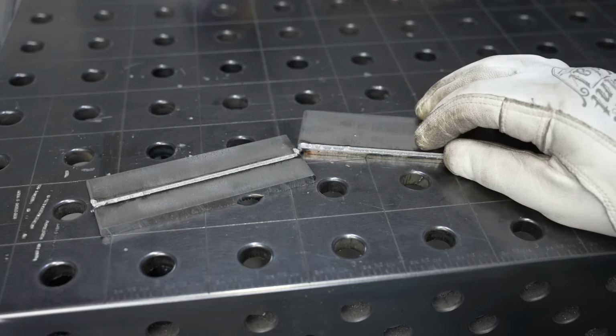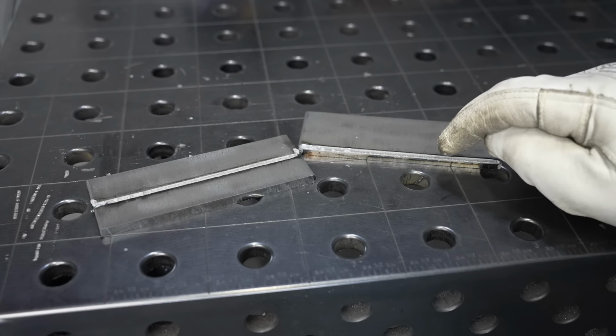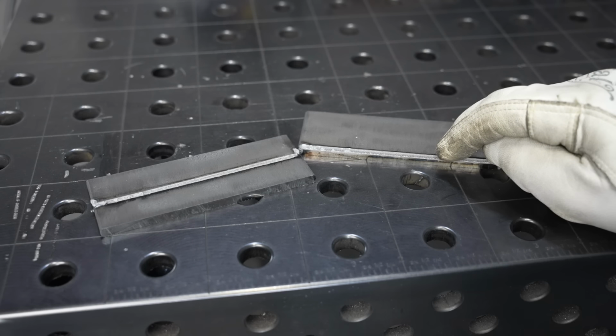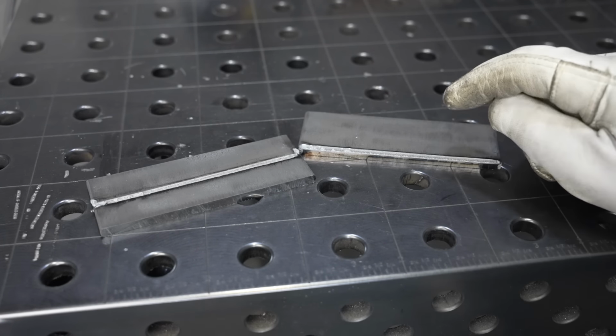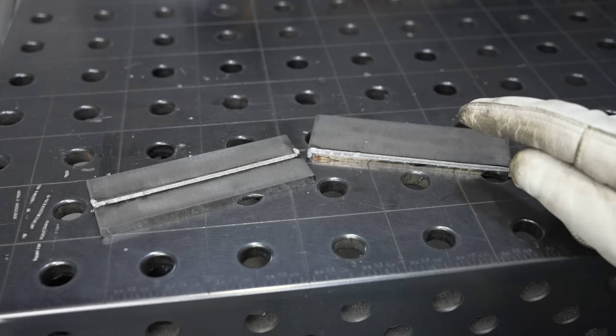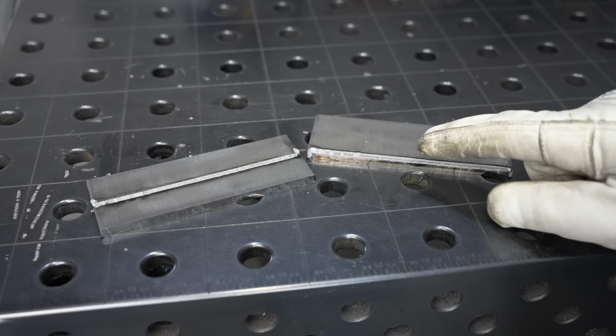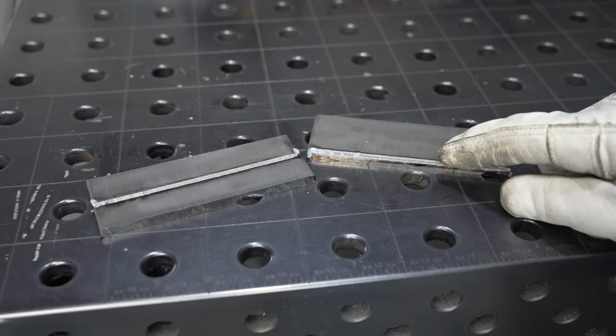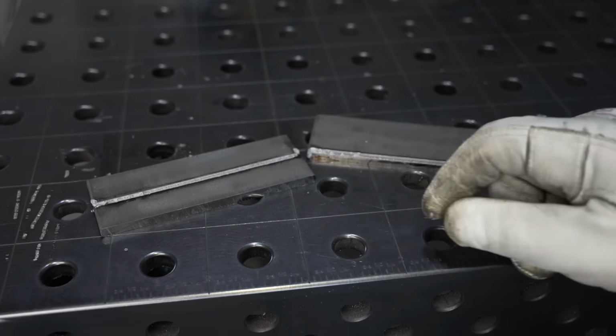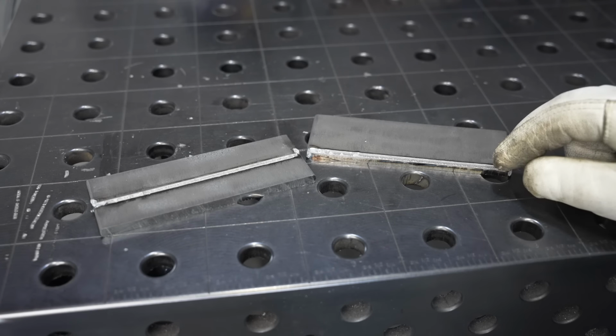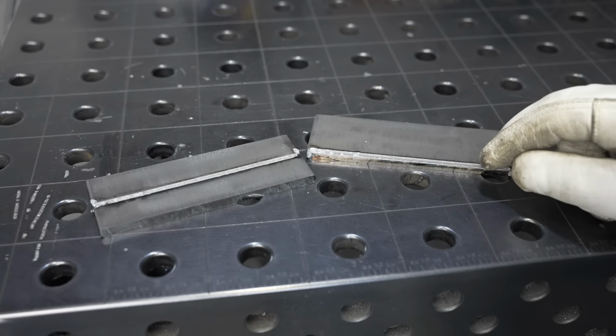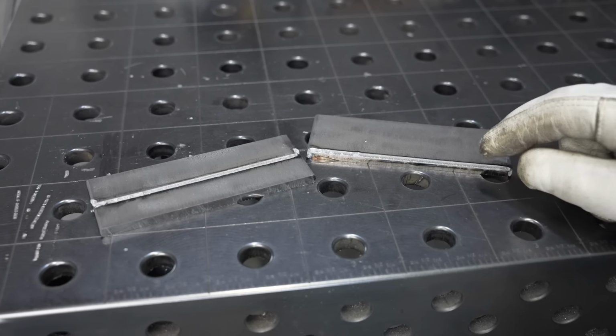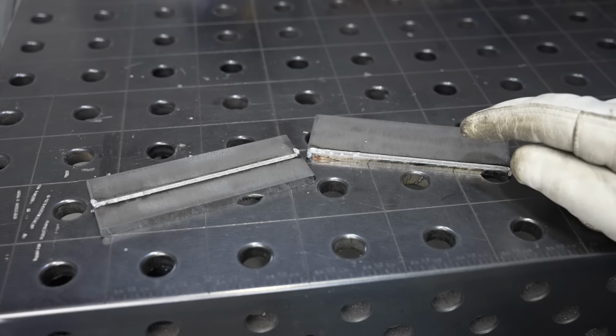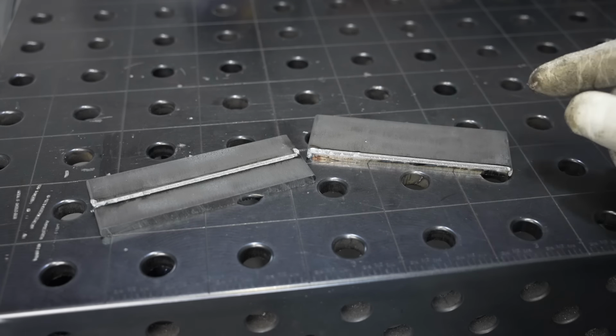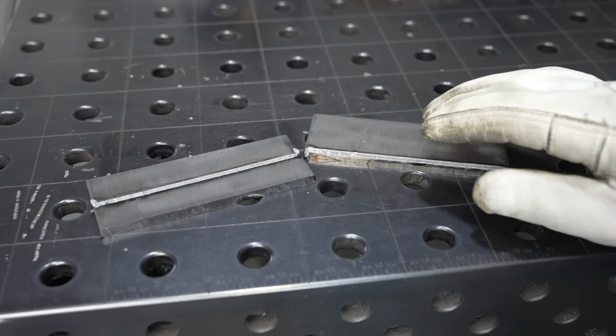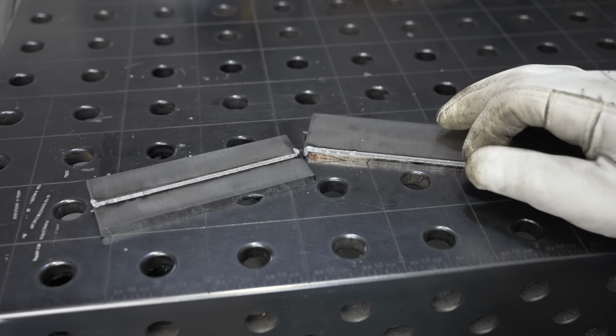That being said, it's a very, very small fillet weld, less than 1/8 of an inch. And that's just too small for pretty much anything structural along 1/4 inch. So a little machine like this with a single wire feed just isn't going to get it done on this thicker structural. And yeah, you could run a bunch of passes and probably get one that was big enough, but that wouldn't make any sense. There's no advantage over running just a MIG weld. Now, with a bigger machine and twin wire feed, you probably could do it, I think. But this one's probably a no-go on 1/4 inch for me, unless it was some kind of decorative thing.